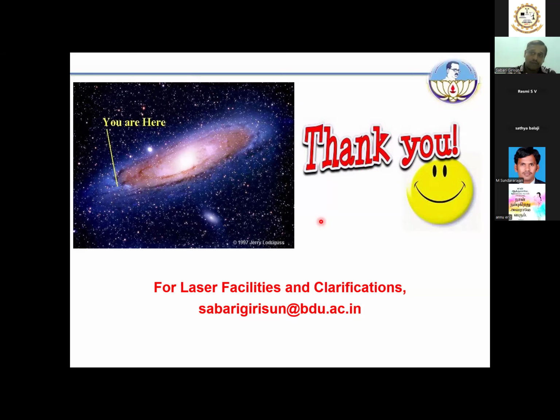And what we have demonstrated with that material is, by theory, linear absorption should become non-linear absorption. So linear absorption becomes saturable absorption. And when I increase the intensity, this saturable absorption should become reverse saturable absorption, right? And when a material goes from saturable absorption to reverse saturable absorption, it should pass through a process called excited state absorption. It should undergo a sequential process and only then move to genuine two-photon absorption. This is the theory available in nonlinear optics, and we have demonstrated it experimentally in our laboratory. Hope I have answered the question.